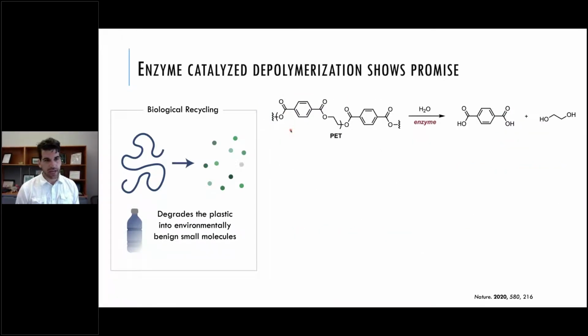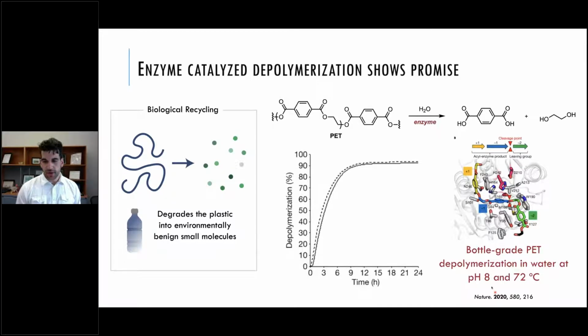Another way to biologically recycle materials is to actually engineer enzymes to cut up polymers. So this is PET. This work has been going on for a long time, but actually a recent Nature paper came out that is more and more viable. So what they found is they engineered an enzyme that could degrade bottle-grade PET, so this is crystalline PET, in water at pH 8 at 72 degrees Celsius. And you can see the depolymerization of bottle-grade PET at a reasonable rate.